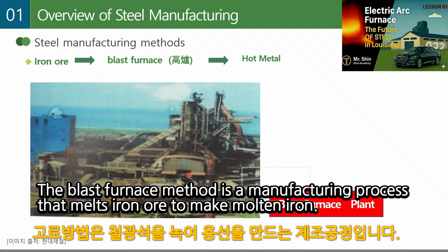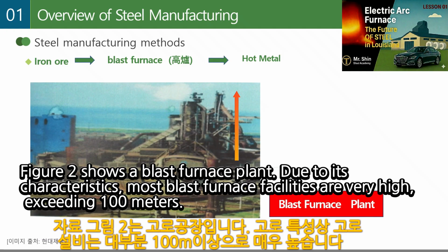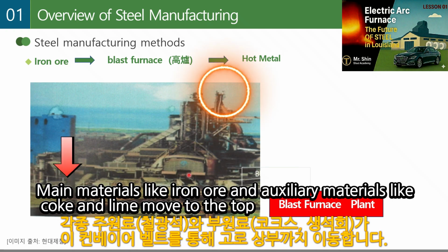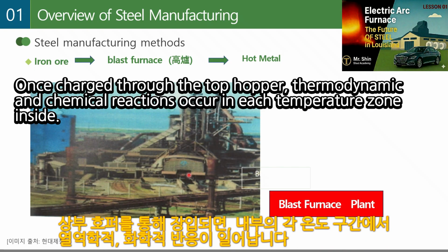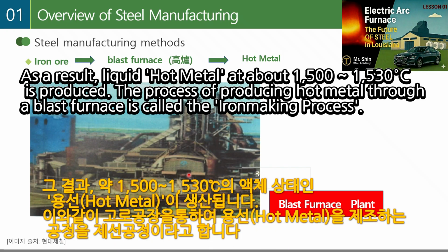The blast furnace method is a manufacturing process that melts iron ore to make molten iron. Figure 2 shows a blast furnace plant. Due to its characteristics, most blast furnace facilities are very high, exceeding 100 meters. Main materials like iron ore, and auxiliary materials like coke and lime move to the top. Once charged through the top hopper, thermodynamic and chemical reactions occur in each temperature zone inside. As a result, liquid hot metal at about 1500 degrees Celsius is produced. The process of producing hot metal through a blast furnace is called the iron-making process.